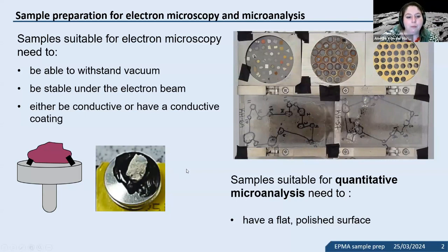The lowest effort sample preparation that you can do is just taking your material and applying it on an SEM stub and coating it. So here are some examples which would allow you to image the sample and maybe get a rough idea what elements are in there. However, if you want to do analysis both on a scanning electron microscope with EDS and on an electron microprobe, you need a flat and polished surface. In addition, usually we have to cut down the samples because the space that we have for the size of samples is usually much more restricted in an electron microprobe compared to a scanning electron microscope.